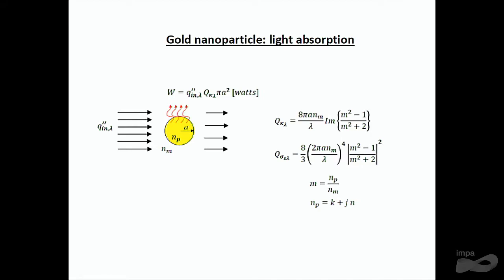The amount of energy absorbed by the particle and later released as heat can be easily calculated using light scattering theories. So you have essentially the absorption efficiency that is dependent on the radius of the particle and the refractive indices. So it's the size, as I mentioned before, and the optical characteristics of the material. Also on the wavelength of the incident light. This efficiency multiplied times pi, the radius squared, and the density of energy that we are imposing on the particle may let you calculate the amount of energy that is absorbed by the nanoparticle and that is released as heat immediately.